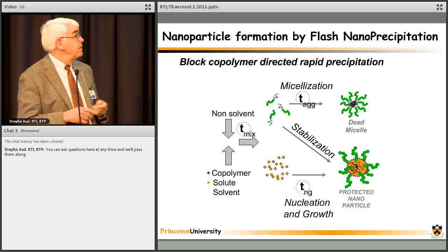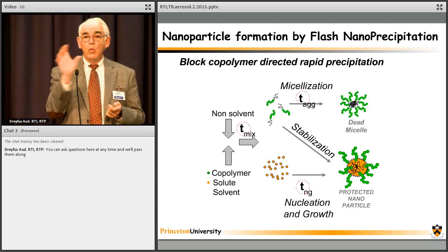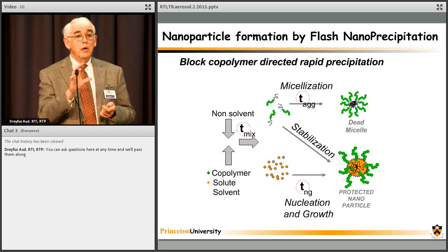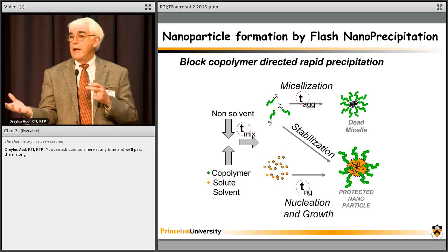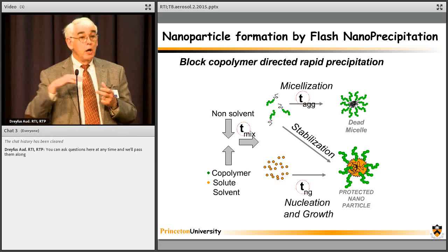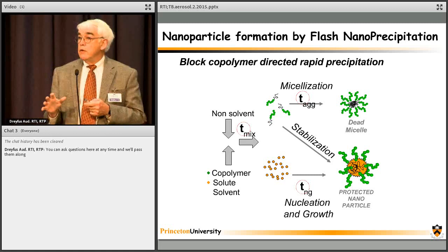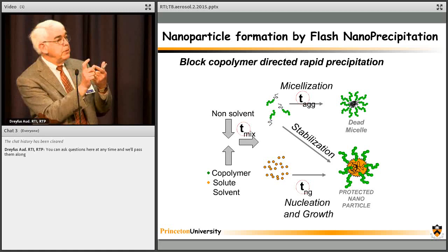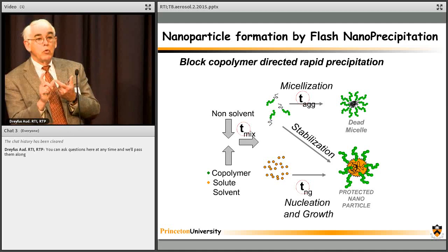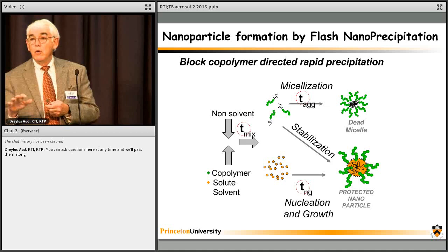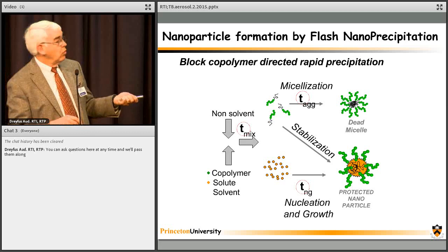We also want polymers here which are so hydrophobic that once they attach to the surface, they never come off. So things like surfactants don't work, because even though you may be able to make a stable particle in vitro, when you put this in an animal or a person, what happens? That thing partitions on and off, and so it will leave the particle unprotected, and it'll end up, therefore, destabilizing the particle. Things you might think of like pluronic polymers or surfactants, if you're familiar with those, are polyethylene oxide, polypropylene oxide. They don't work because even though you can make nice particles in vitro, they have a relatively high solubility. They're coming on and off the particle all the time, and so in vivo, they will partition off and leave the particle unprotected. So we want things that are big enough that once they are adsorbed, they're irreversibly captured and they never come off. And we'll describe a few of those polymers a little later.